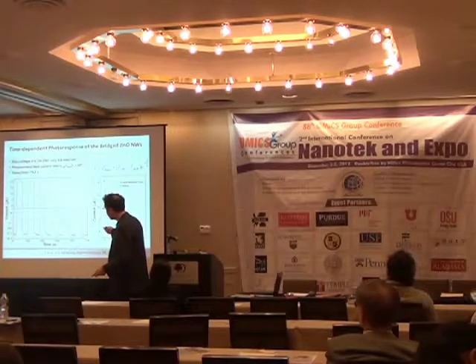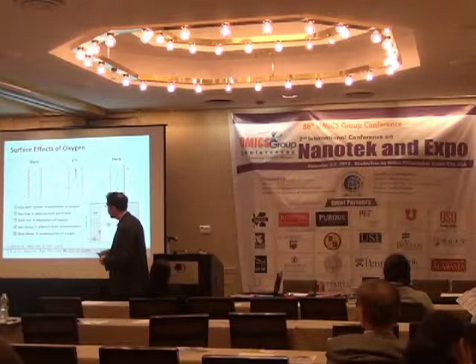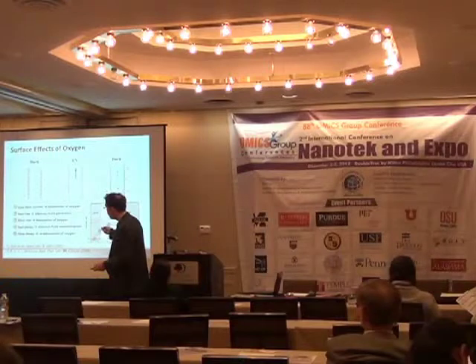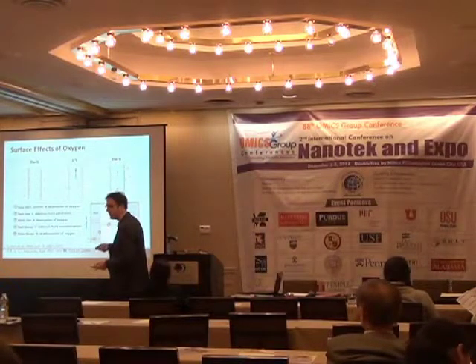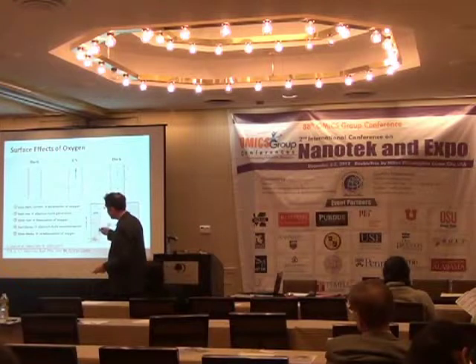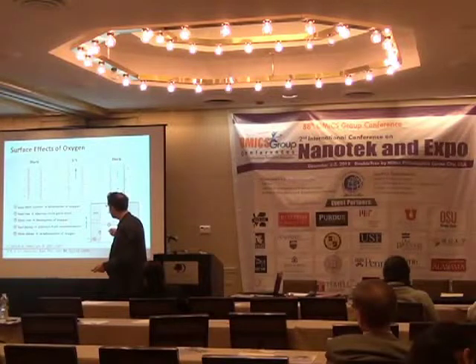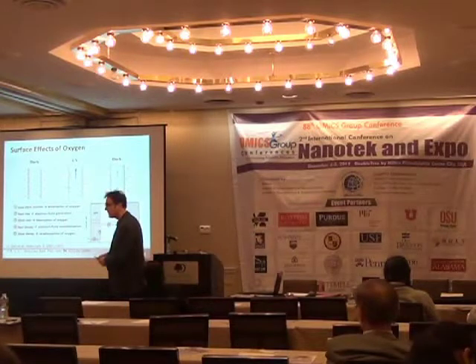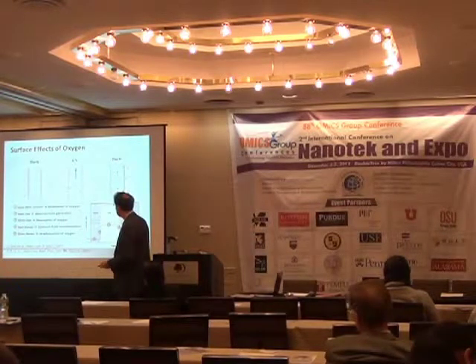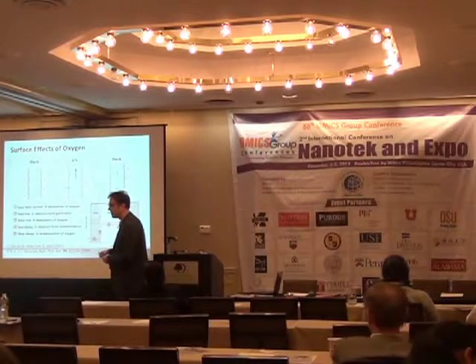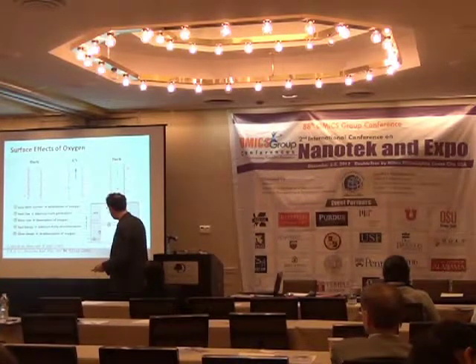You get a slow rise here, and a slow decrease here, and they are both explained by kinetics, in the sense that oxygen molecules trap electrons and deplete the zinc oxide nanowires of electrons. That's what you have in the zinc oxide. When you illuminate with UV, the oxygen is desorbed, and this is the slow reaction because this is kinetics. Then when you put it back in dark, the oxygen is reabsorbed. That's what you see here for the reabsorption and here for the desorption.